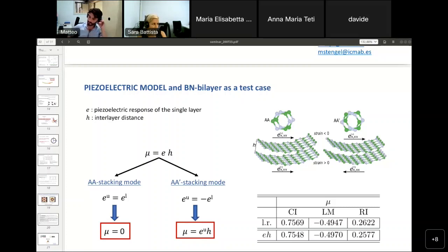Okay. About the first question, yes. Depending also on the direction that we consider, I would say it makes sense to speak about polarizability, because I think it can be related to the quantity that we studied, depending on the definition as well. Basically, if we manage to relate it, for example, to the voltage drop that we define, or in the case of the in-plane response, to the polarization, it could be harder to properly define it. But for example, in the first work, the one concerning the out-of-plane response, we actually noticed that, in some way, the out-of-plane response is related to the polarizability of the material in that direction.